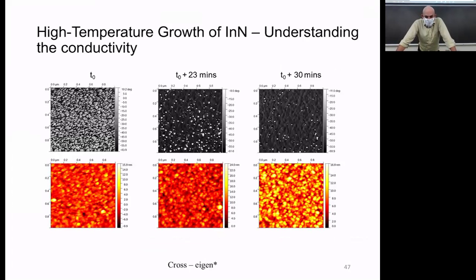So we were not able to measure some of these samples at first because they just were not working, and we were getting this double imaging the whole time. We replaced 3 or 4 AFM tips because, well, you know, it could be the AFM tip, might not be sharp enough, might have broken it, who knows. And what we started to do was we looked at the phase of the AFM image. And what the phase does is it tells us how, quote unquote, sticky the sample is. And it turns out that the sample had 2 stickinesses. That's not a very technical term, I understand.